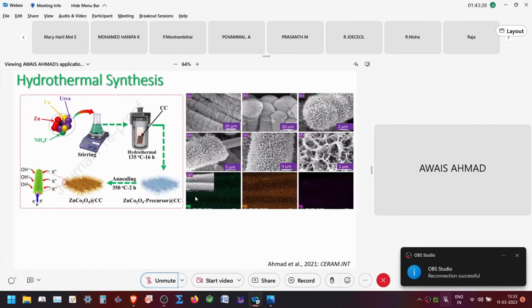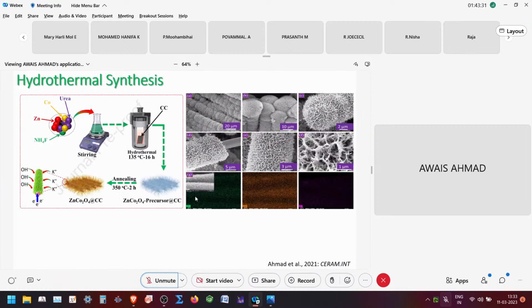Again, there is a hydrothermal synthesis with zinc, cobalt, and urea. Why urea? Because it was a stabilizing agent. Again, we get some sort of hexagonal shapes in our nanomaterial. That paper is published in Nano Energy. Then we combine zinc and cobalt, and again with the urea, and we fabricate it on a carbon cloth electrode, and at the end we get nanosponges. And here you can see how beautiful they are.